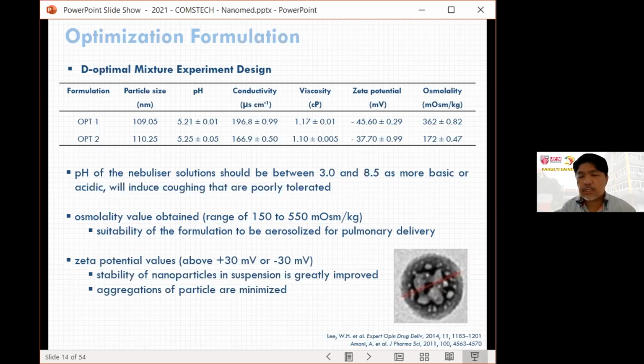we still focus on this because we do not want our formulation to be aggregated. We have to make sure it is stable for at least 90 days. There are works that we carried out up to 6 months, but normally for the standard, we run it up to 90 days or 3 months.